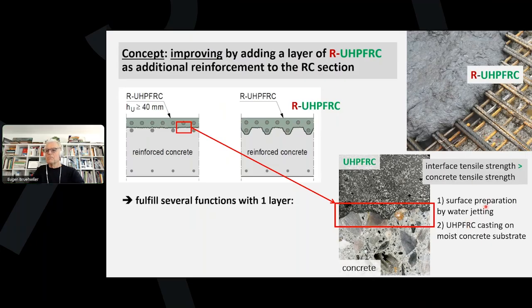And if we fulfill these very important and basic requirements, then we can perform tests, we can perform pull-off tests, and these tests will show that the interface tensile strength here along is stronger than the concrete tensile strength. In other words, when we pull on this composite system, it's always the substrate concrete that is the weakest link, the substrate concrete that will fail.